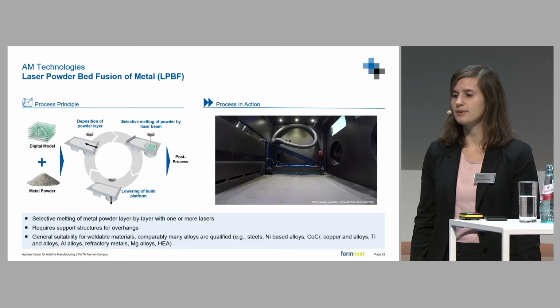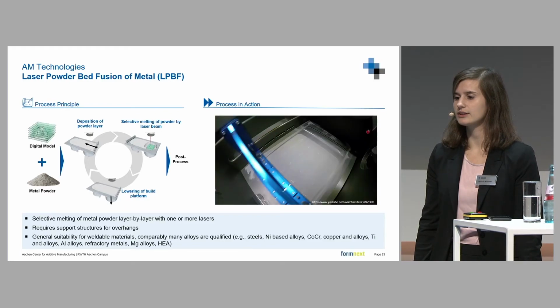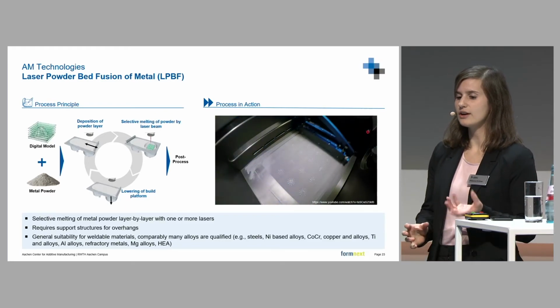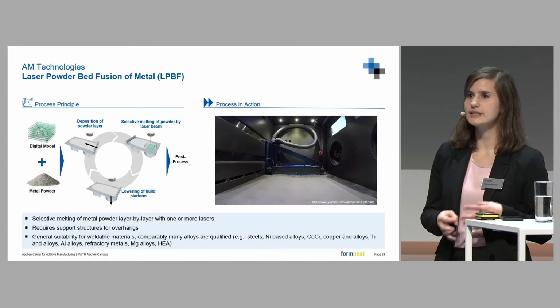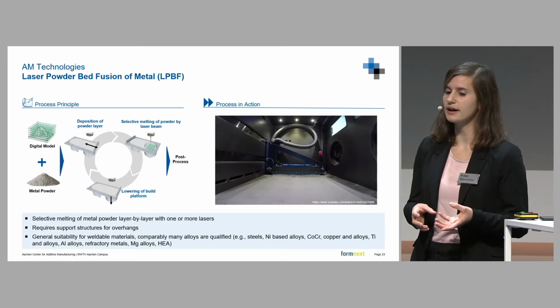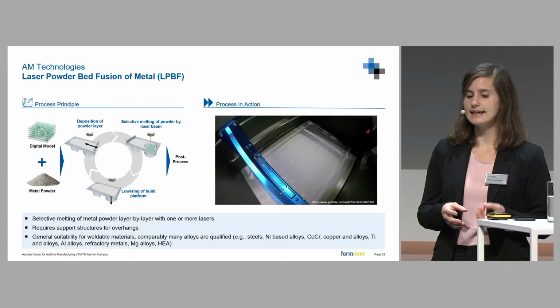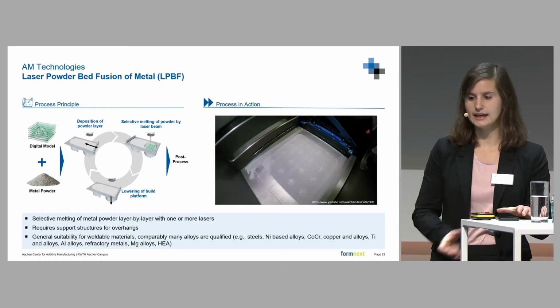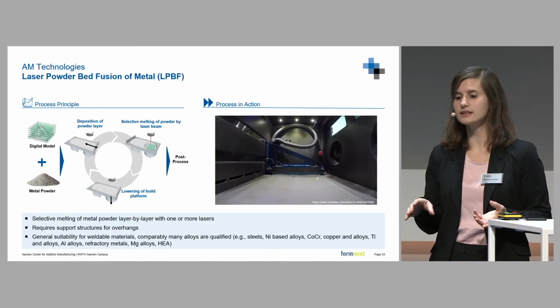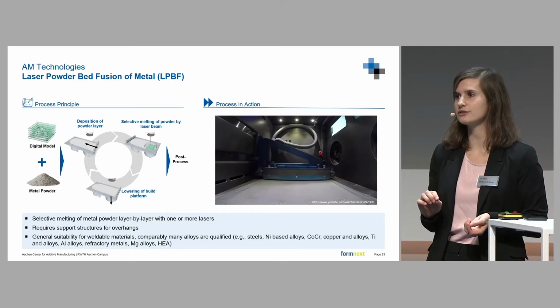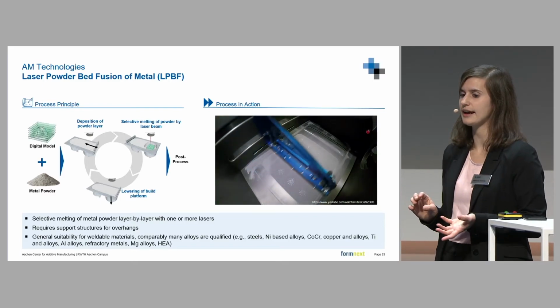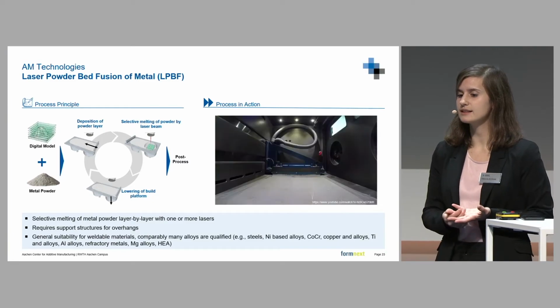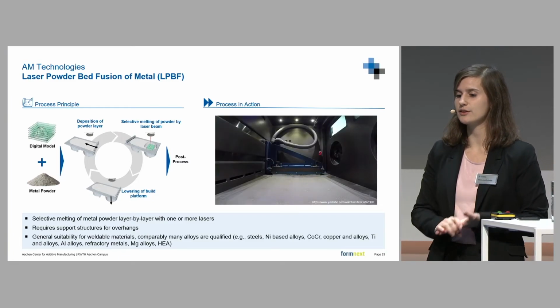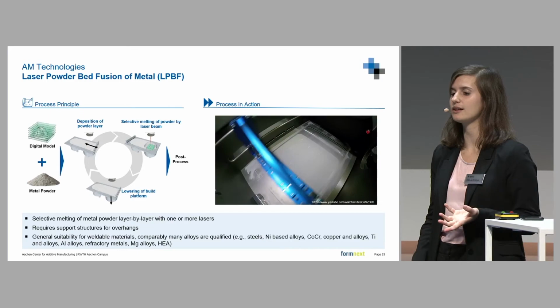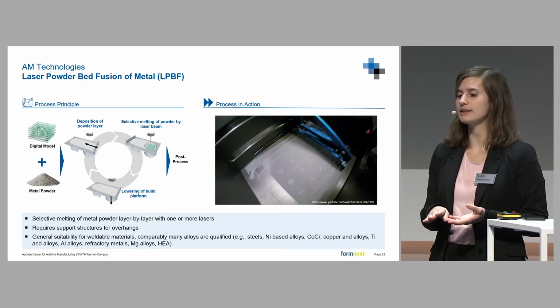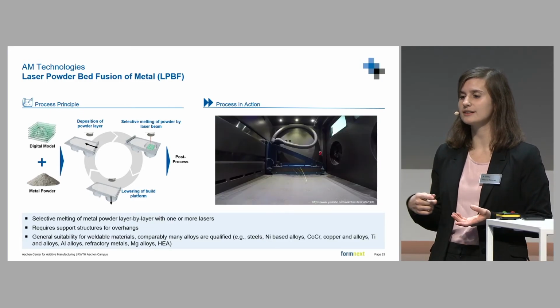So if we look at laser powder bed fusion, on the right-hand side you can see the process in action. How does it work? As input, you have the digital model, the digital data of the part, and you have metal powder. Powder is deposited, just one layer of powder according to the thickness of one layer you want to have. And it's selectively melted by means of a laser beam, like you can see on the right-hand side. And then the build plate is lowered exactly by one layer thickness, and the whole process starts again.